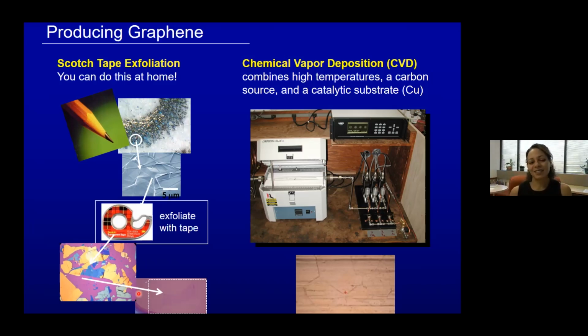And these days, it's also made using chemical vapor deposition, which is a relatively simple deposition system that combines high temperatures, a carbon source, and a catalytic substrate, typically copper. That allows you to grow graphene on pretty large areas. This is what we generally use because then we can transfer it onto different types of substrates.